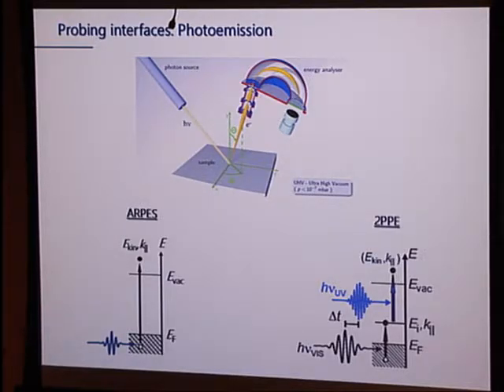You collect them as a function of angle. That gives you band structure because the momentum has to be somehow conserved, at least the in-plane momentum. And then you energy filter them with a hemisphere, for example, where you apply a radial electric field and then collect them. You can do this with very high sensitivity. This is an electron counting setup where we see one electron at a time. Now, the standard way to do this is what we would call ARPES, or angle-resolved photoelectron spectroscopy. Photon comes in, electron comes out. You measure the kinetic energy and its momentum.